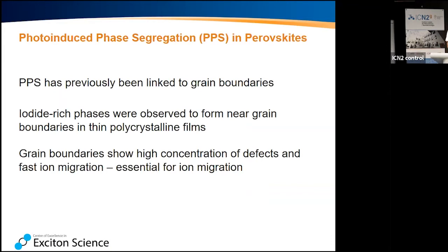So what happens is that we create these small centers that are very, very rich in iodide. And we don't have a homogeneous material anymore. So we have a material that has bromide-rich domains and iodide-rich domains. And because it's not homogeneous, the electrical and optical properties are also not what we want from it. So that usually is a bit of a problem.